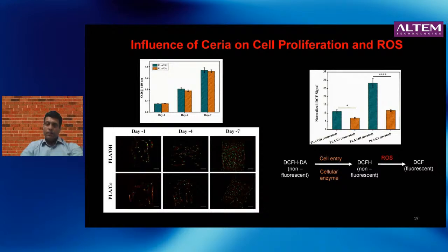However, if you look at the ability of these scaffolds to scavenge ROS, that was very different because the one with the Ceria could do it, whereas the other one obviously doesn't do it. So here what we've done is we've added a dye which will measure how much ROS is there. If there's more ROS, it will look more fluorescent, and by looking at the fluorescent signal, we can tell if there is reduced ROS quantification or not.